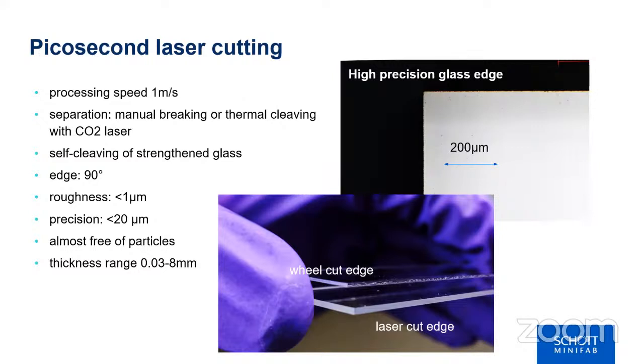The laser cut edge is slightly frosted. The precision is given by the machine technology in the order of 20 microns, but 20 microns on a meter scale. And it's almost free of particles. So you see the image here is directly taken after the cutting process in the production hall. So the particle load is quite low.